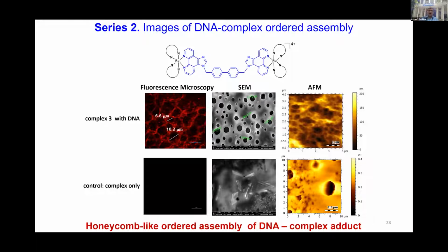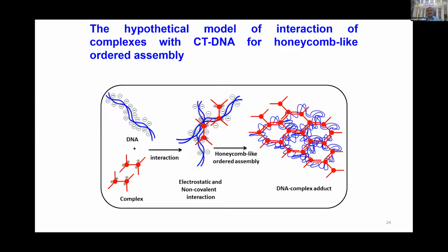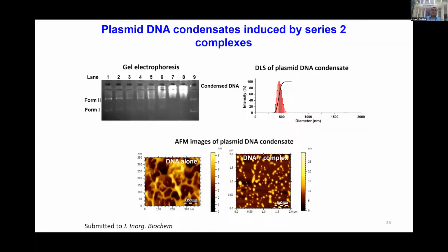These complexes, a hypothetical model of their interaction is shown over here. DNA, being polyanionic in nature, interacts with the positively charged metal complex through electrostatic and additionally non-covalent interactions to give rise to a honeycomb-like ordered assembly to form a DNA complex adduct. These condensates have also been seen in gel electrophoresis to form a condensed DNA structure. The plasmid DNA condensates have a size of about 500 nanometers, and the AFM images also indicate the DNA condensates.